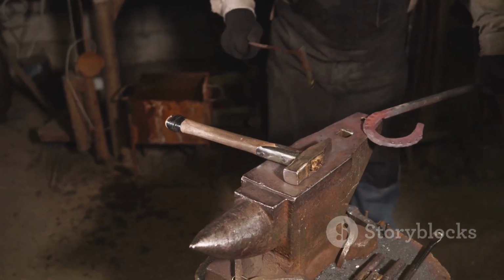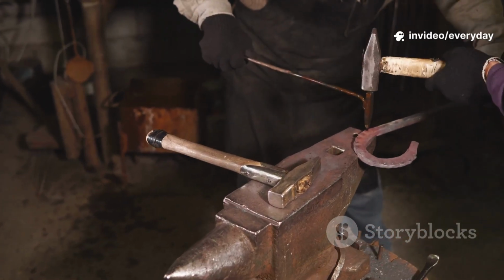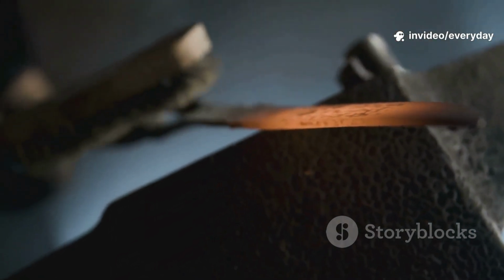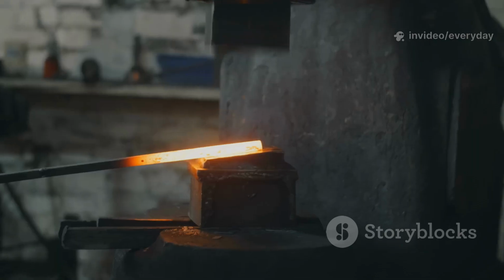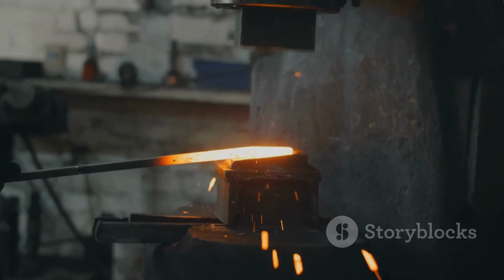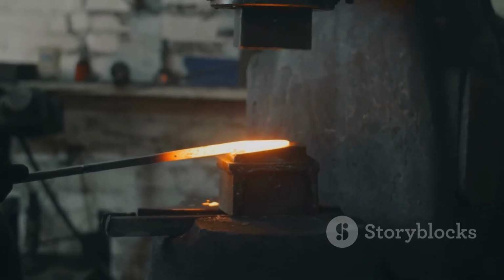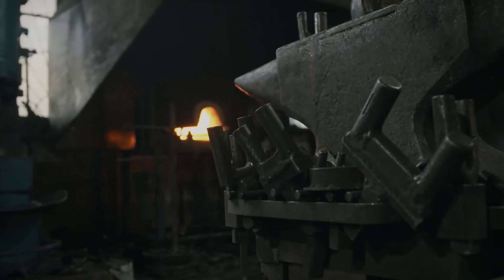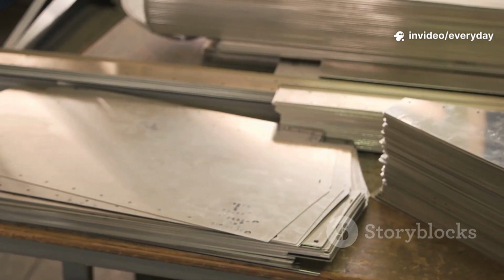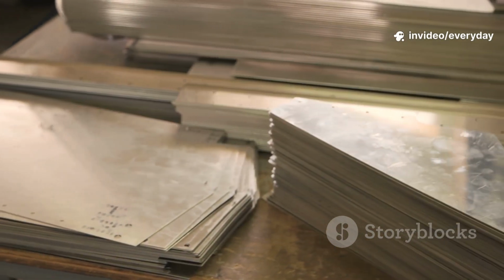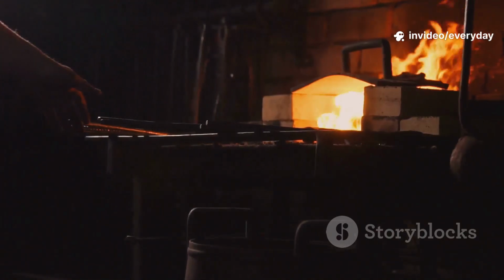Add small tacks or tight wire to keep layers aligned for heat. Brush off grinding dust. Some wipe with acetone. Let it fully evaporate. It may feel excessive, but clean prep is the secret to consistent welds. Minutes spent now save hours of frustration later. A clean start gives you a homogeneous billet, the bedrock of a great blade. Now the fire can do its work.